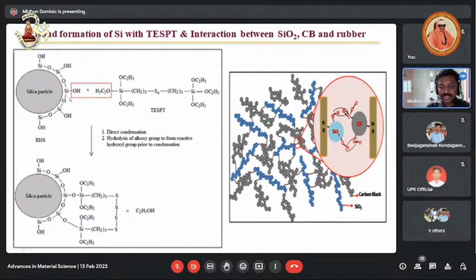So we know that silica is hydrophilic in nature and natural rubber is hydrophobic in nature. In order to improve the compatibility, the interaction between the silica and natural rubber, we have to make use of a coupling agent. TESPT is the commonly used coupling agent in tire formulation, and it reacts with the silanol OH groups, OH and OC2H5. The ethanol molecule gets eliminated and the silica particles are connected with the TESPT, and the sulfur can be involved in cross-linking. So this is the method by which commercial silica can be connected to natural rubber.